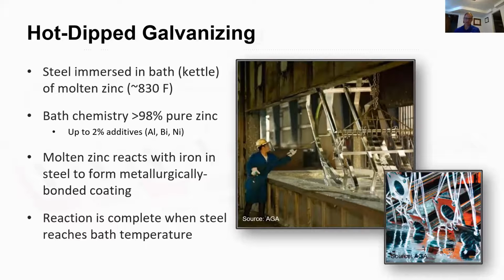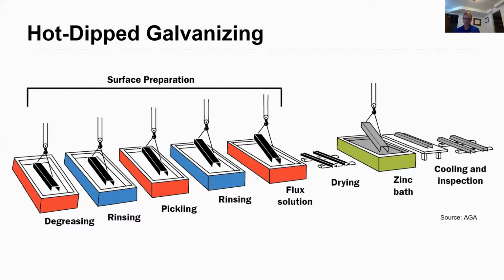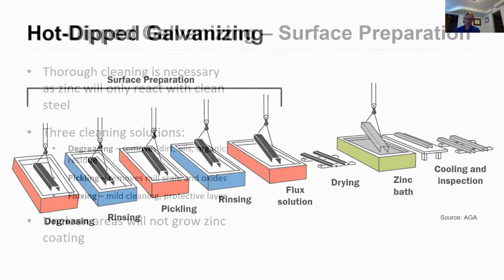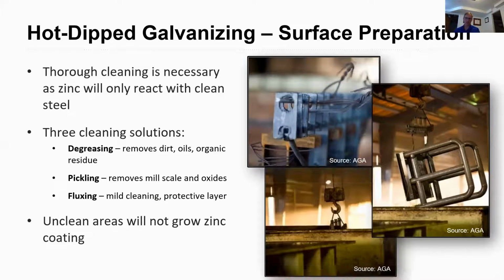This is a little bit on the surface prep that goes into this. There's three major stages of surface prep: degreasing, pickling, and fluxing. And then after that's done and it dries, it can be dipped into the zinc bath. But only then can it actually be dipped into the zinc bath. And this is a little bit more information on what happens in these various stages of surface preparation. Degreasing just removes dirt and oil and any organic dirt, if you will. Pickling removes any mill scale, which in a paint system, for example, is taken off by a wheelabrator. And fluxing is just a mild cleaning and then a protective layer. But if you don't clean it properly, then the unclean areas won't grow a zinc coating. So that's very important to the overall process for hot dip galvanizing.